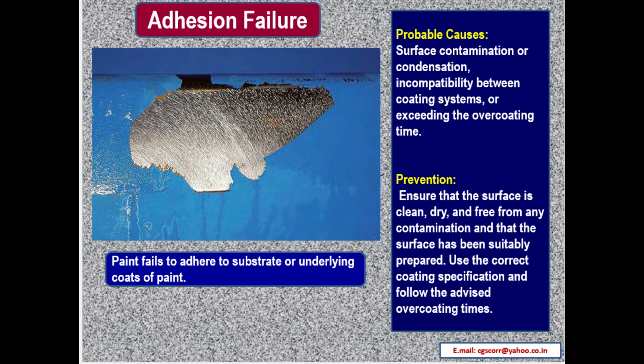The next one is adhesion failure. The figure on the left top side gives you a picturesque view of adhesion failure. The paint fails to adhere to the substrate or underlying coats of paint. Probable causes: surface contamination or condensation, incompatibility between the coating systems, or exceeding the overcoating time. Prevention: ensure that the surface is clean, dry, free from any contamination, and that the surface has been suitably prepared. Use the correct coating specification and follow the advised overcoating times.